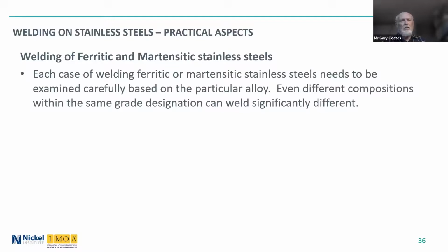So in summary, for the ferritic and martensitic alloys, each case of welding ferritic or martensitic needs to be examined carefully. It isn't a case of, well, I can use my general rules and I'll be safe. No, you need to really look at what particular alloy you want and what properties you want of the heat affected zone, especially, and the weld metal. And even different compositions within the same grade can weld significantly differently.